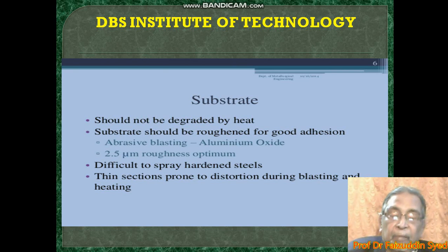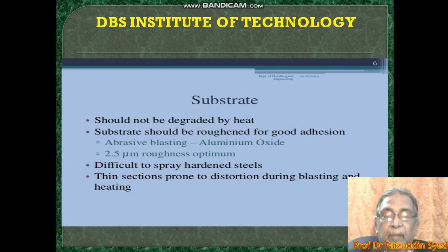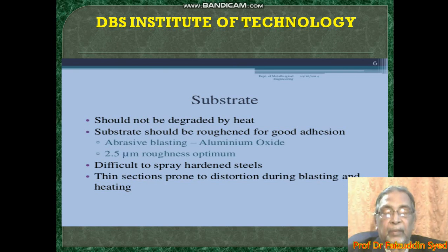You can do abrasive blasting with aluminum oxide. The abrasive blasting with aluminum oxide may be coated up to 2.5 microns roughness, which is optimum. It's difficult to spray hardened steels, because they are so hard that the spray may not be able to attach perfectly. Thin sections are prone to distortion during blasting and heating. Suppose you want to spray on thin sections, they may get distorted during abrasive blasting, so you should take more care in these operations.